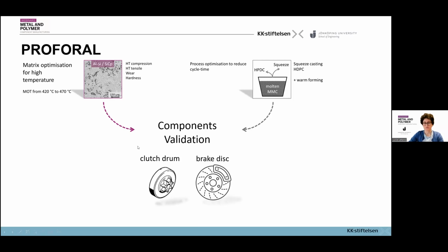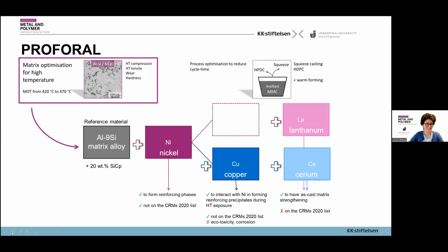Then the second step is to look at the process optimization to try to reduce cycle time. The brake discs are currently produced with squeeze casting, which is an excellent technique, but we wanted to see if high pressure die casting combined with warm forming could let us gain a little bit of time in the cycle production. And then at the end, we looked at the components of interest. In this case is clutch drum for the Husqvarna side and brake disc for the AC Flubi side to really see if this material is really promising in this case.